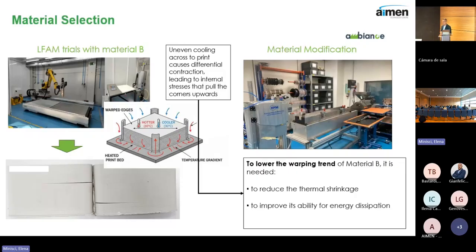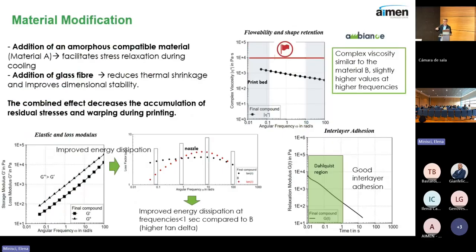How do we do it in AMBIANCE? Basically, here we blend the original material B with another material with a more amorphous nature, so increasing the viscous character of the blend. So we did, of course, many different trials, adding different amounts of fillers and different fractions of the amorphous material until we got the sweet formulation, the one that we could print in the large format without suffering